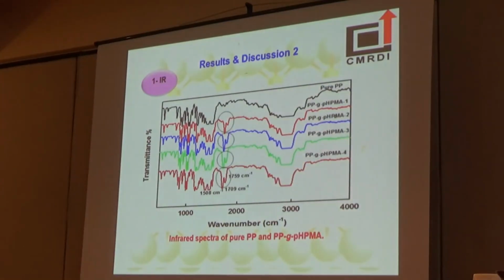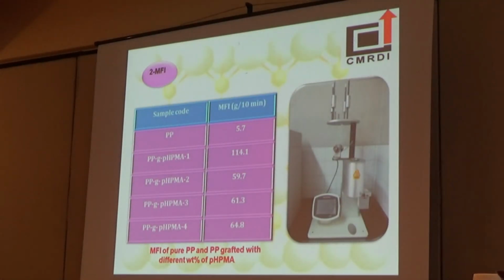Results and discussion. The infrared spectra of pure polypropylene and polypropylene grafted samples show the appearance of two new peaks for all the grafted polypropylene samples, and their intensity increases with increasing amount of the added monomer, which indicates the grafting reaction. Melt flow index measurements are usually used to determine the ease of flow of a material and its viscosity.